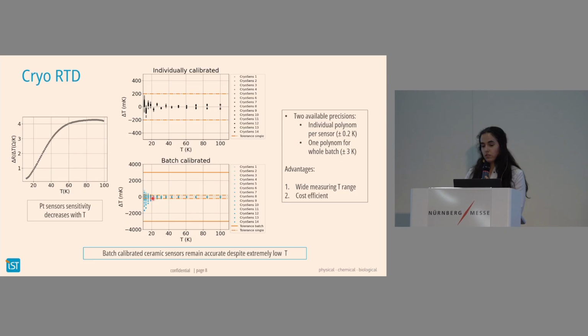So this showed us that we can use platinum sensors down to extremely low temperatures, and they can be done in two available precisions. Either we deliver an individual polynomial for each of the sensors, and then the precision would be plus minus 200 millikelvin, or we have one polynomial for the whole batch, and this would be 3 Kelvin. The advantages of this is that this is a very cost-efficient solution, and that one can use the same sensor for a very wide temperature range.